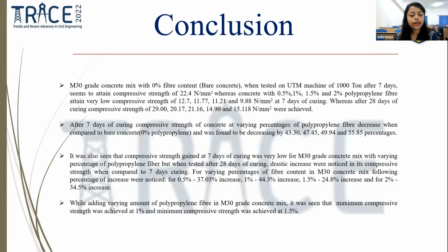Secondly, after 7 days of curing, the compressive strength of concrete at varying percentages of polypropylene fiber decreases when compared to bare concrete and was found to be decreased by 43, 47, 49, and 55 percent. It was also seen that compressive strength gain at 7 days of curing was very low for M30 grade concrete mix with varying percentages of polypropylene fiber.